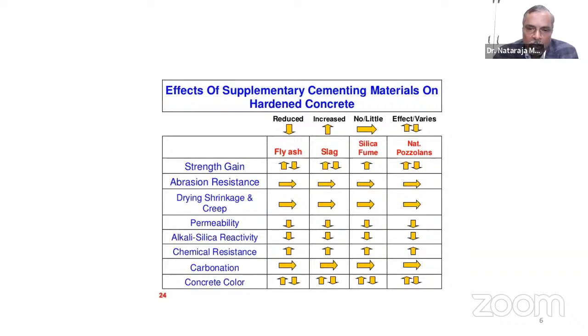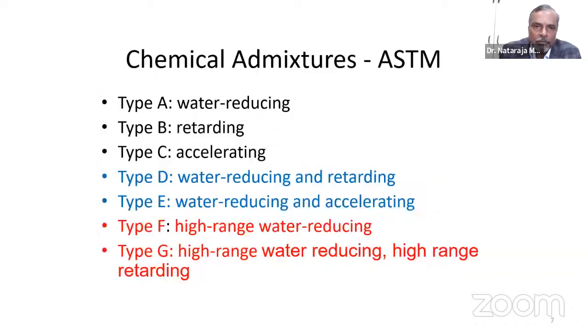And even the abrasion resistance of the concrete will be better. Drying shrinkage and creep will be better with the addition of these supplementary materials. And as many of you must have appreciated, the permeability of the concrete also decreases substantially due to the addition of these supplementary materials, individually or as a combination. The chemical resistance definitely improves. As far as carbonation is concerned, some people have said that carbonation might be affected when you have a combination of supplementary materials, but otherwise it does not have much significance; that's where the arrow is almost horizontal. These are all some of the advantages of using supplementary materials in the production of any type of concrete from the point of view of hardened properties.